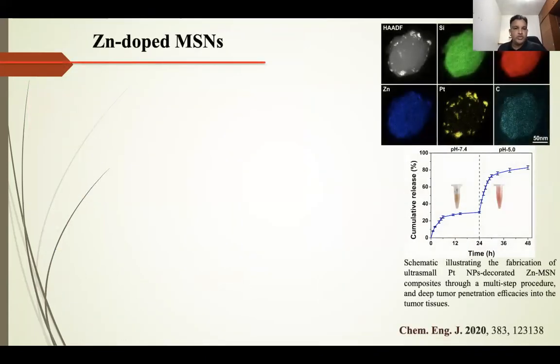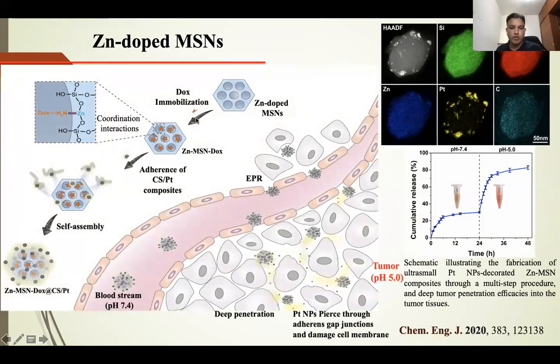So in another case, we tried to replace the copper with zinc, and in a similar way we tried to create the same story here. Even zinc shows the release of DOX specifically in the acidic environment, where you can see the DOX was immobilized inside the silica frameworks, and this zinc-containing MSN with DOX is coated with CSPT, the chitosan encapsulated with PT nanoparticles, coated over the MSN. Here it is not the free radical chemistry, but we try to make an entry into the MDR cancer cells, like the creation of a pathway.